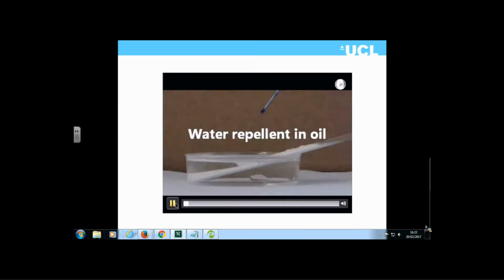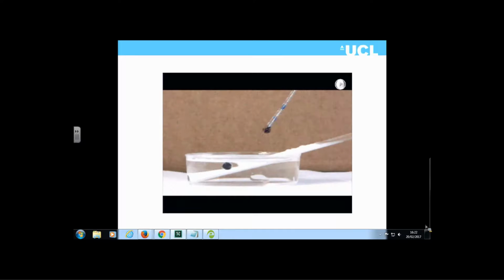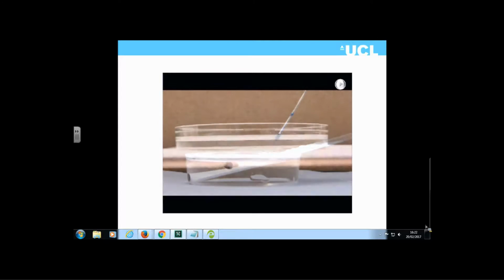So we can also get the surfaces to be water repellent in oil. This is dropping water droplets into an oil beaker, and it shows that the water doesn't wet the surface for our superhydrophobic surfaces.